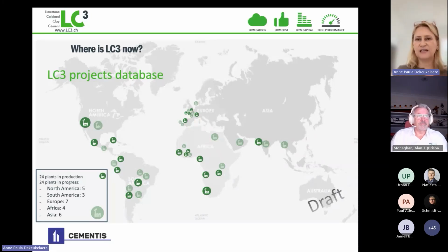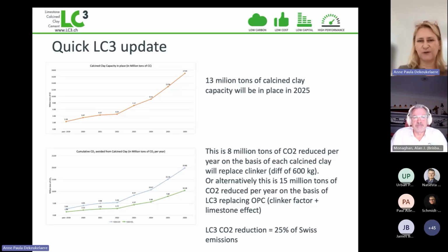And we even did the calculation, which means that until 2025, 13 million tons of calcined clay capacity will be in place. Depending on the calculation we do, this means between 8 million tons of CO2 reduced per year or 15. So it's between 8 and 15 million tons of CO2 per year, which is massive. And that's on average 25% of Switzerland as a country, its emissions.